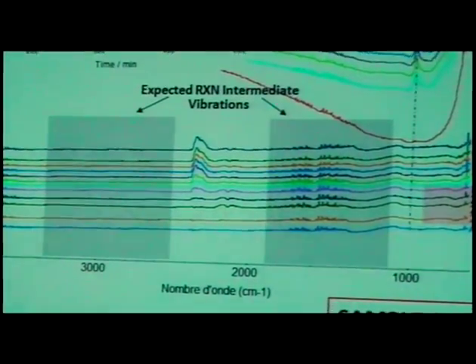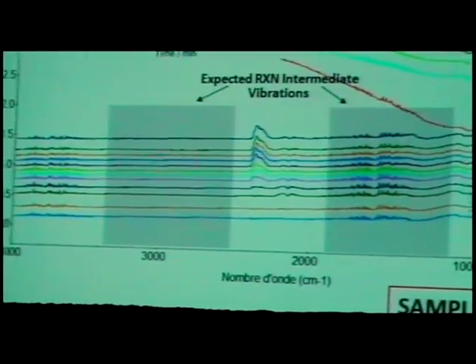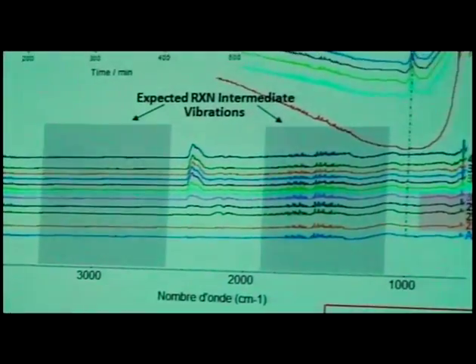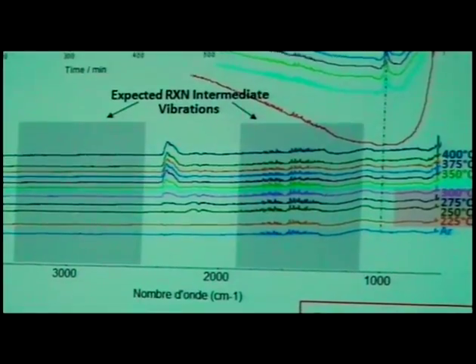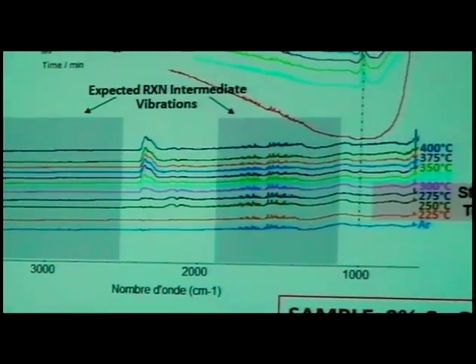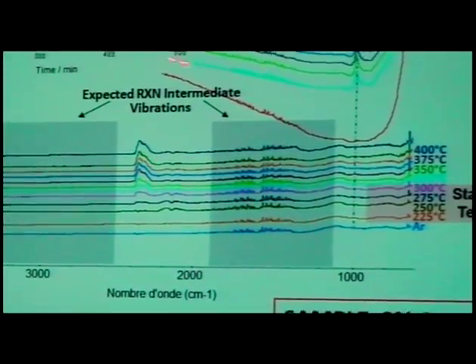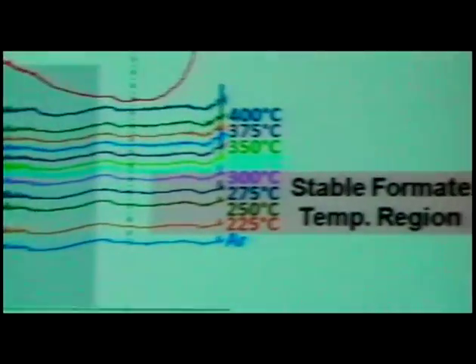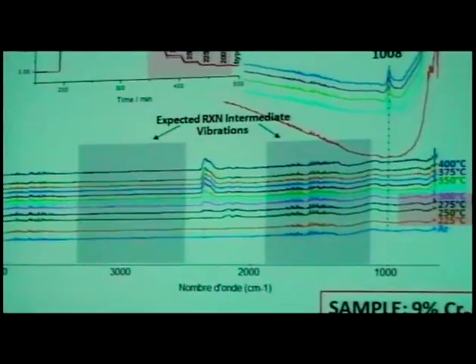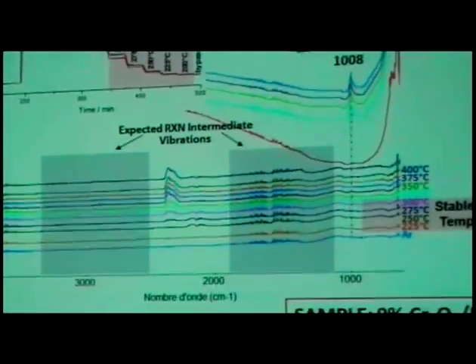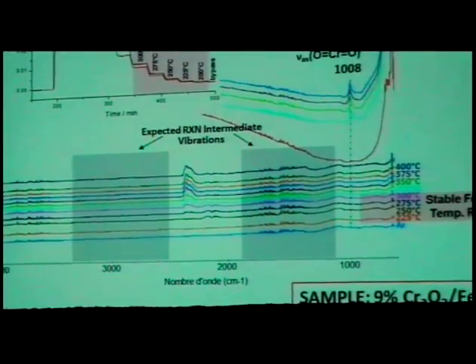We just do not see any formate during the water gas shift reaction, even at temperatures where, remember, the formate was thermally stable till 300 C. So this was a region where we should have seen formate if it were an intermediate, and it was not there. So that is the mechanism. There's no evidence to support the so-called associative mechanism.